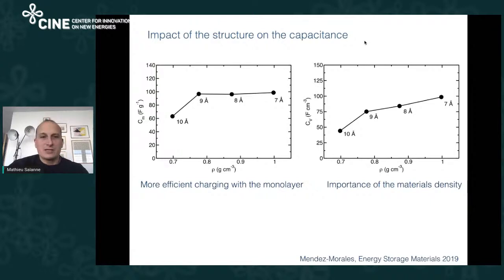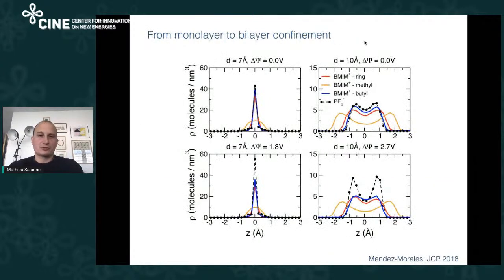In fact, this behavior is because we have a change of structure. When we have small pores like 7 angstrom, we only have one layer of liquid inside the pore, while when we have 10 angstrom, we have 2 layers of liquid. And so in the end, this is why there is a change in capacitance.